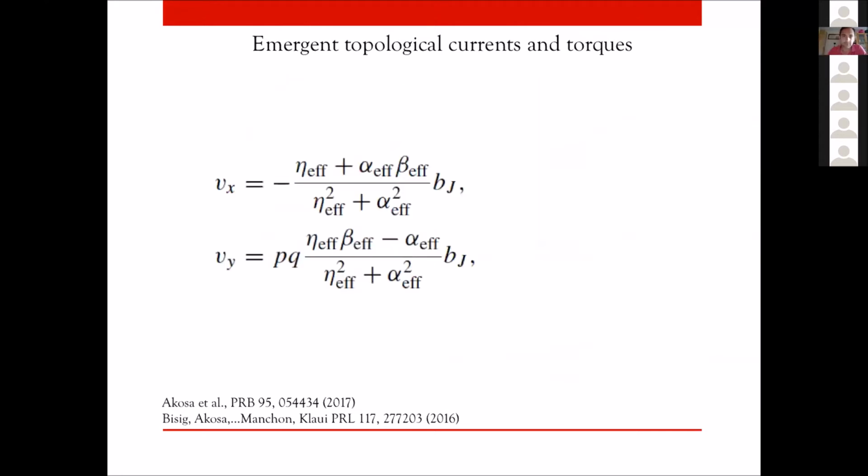So we did some analytical theory. Of course, it's not as good as micromagnetic simulations, but it gives you some good ideas. And we can get the longitudinal velocity and the transverse velocity, in the case of isolated skyrmions, as a function of the electron drift velocity. So this is very well known, and I'm sure this community is very familiar with those formulas.